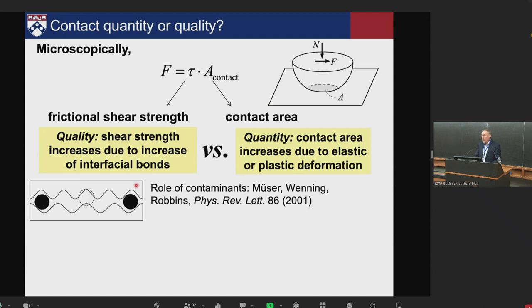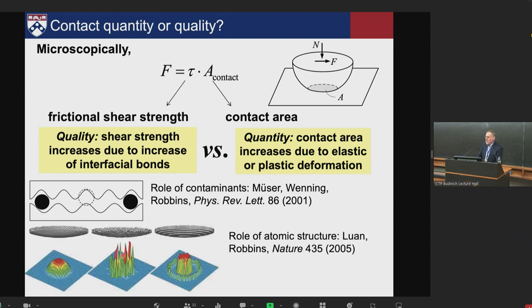If we think about contact quality, it was actually Mark Robbins and Martin Müser who really first pointed out that commensurate surfaces can have high friction, incommensurate would have low friction. Why do we not see vanishing friction all the time? Interfaces shouldn't normally just suddenly be commensurate. Well, for one thing, contaminant atoms will pin the interface. So even an incommensurate surface can have high friction, and this concept is over 20 years old now. Mark also showed another way to think about what happens at the interface. Take the same tip, the same radius, but make it round, make it like a bent crystal, make it an amorphous structure, make it a stepped structure. And the contact stresses that you get are completely different down at the nanoscale. So friction will be different at this scale. So these are just some examples to say the quantity of the contact matters, but the quality matters too, how the atoms are interacting across that interface, how they are structured. And that's going to be the theme of this talk.